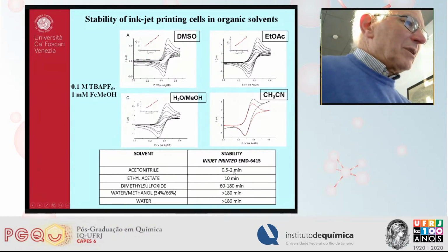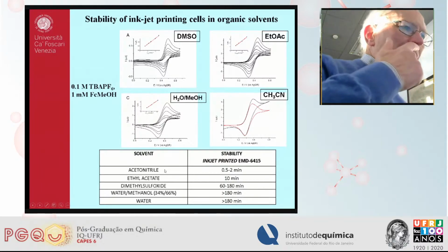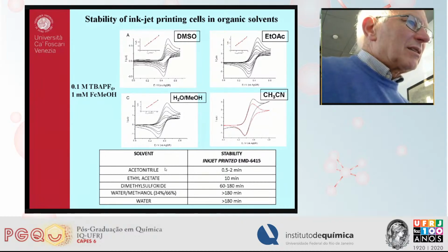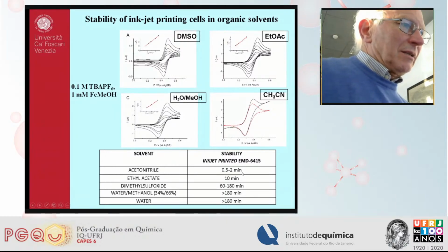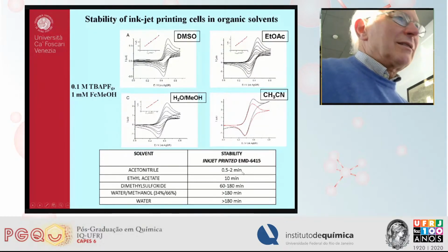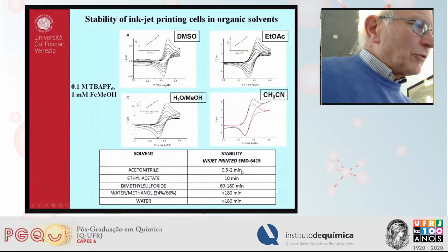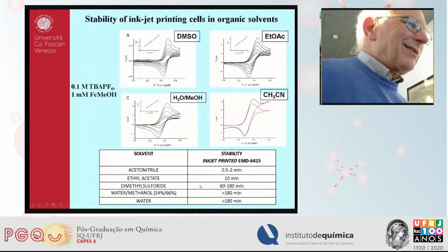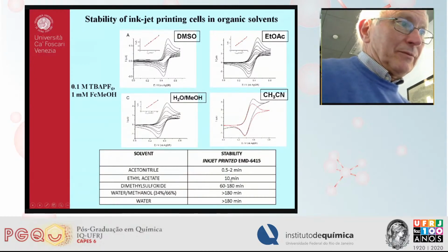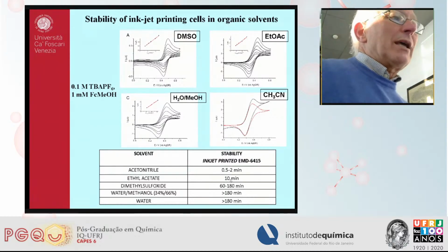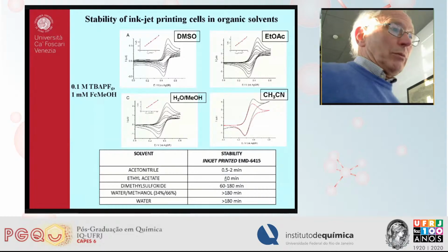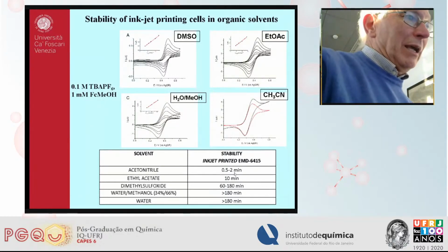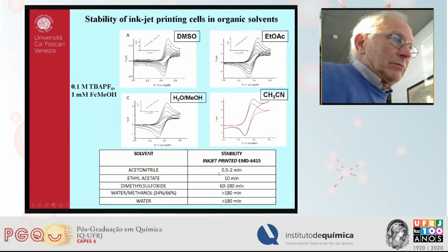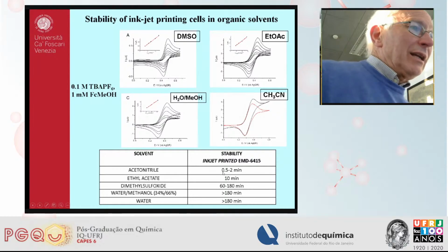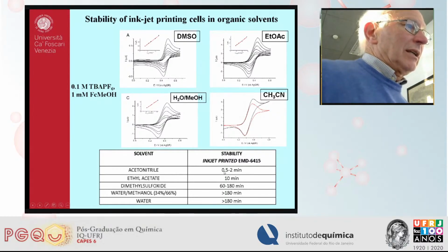So as can be seen here, acetonitrile is the worst solvent even for these inks. The stability is rather low. 1 to 2 minutes is the maximum stability, and after that, the results are really strongly irreproducible. With ethyl acetate, the stability was much better, 10 minutes, which means we could make one measurement, or at least 1 or 2, 3 measurements of the type I've shown you for imatinib. We couldn't make measurements of irinotecan because in acetonitrile this electrode has very, very low stability.